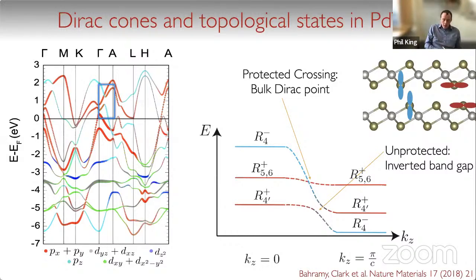Okay, so this is all very nice in theory, but we want to see this also experimentally, and these states are well above the Fermi level. But if you look down now below the Fermi level, you see a rather similar set of states crossing here. Again, this PZ-derived state disperses down and crosses through the PXY, the top PXY state here. There's then a small inverted band gap beneath that. And then actually in these occupied states, there's another inverted gap down below as the D states start to come into play here as well.